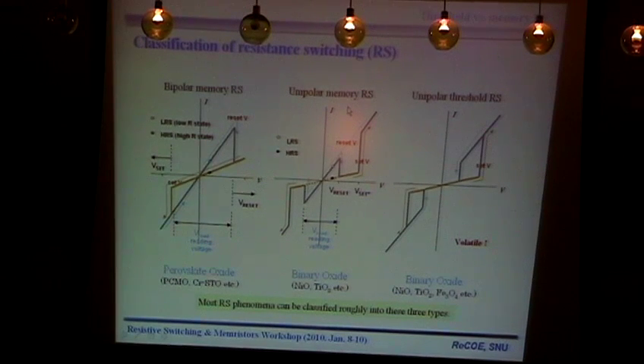For memory resistance switching, they are stable at zero bias, so it's non-volatile. On the other hand, with threshold switching, one of the states is not stable. There is only one stable state at zero bias, so this is volatile. So we can distinguish this one as memory and this one as threshold switching.